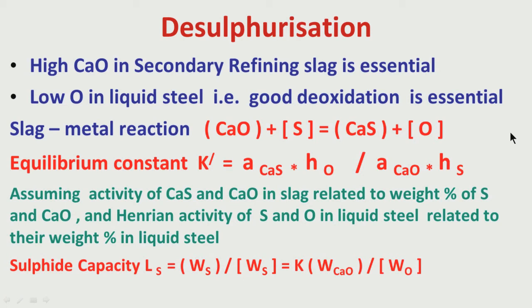So what does it indicate? How will the reaction be faster? It can be faster when we have a very good amount of calcium oxide in the slag and a very low amount of dissolved oxygen in liquid steel, because if you look at the equilibrium constant, it is activity of calcium sulfide times activity of oxygen divided by activity of CaO and activity of sulfur. Now, assuming that calcium sulfide and calcium oxide in slag are related to weight percent of sulfur.